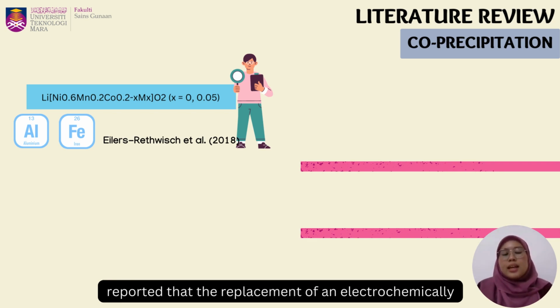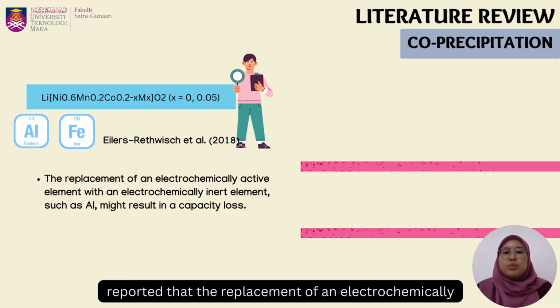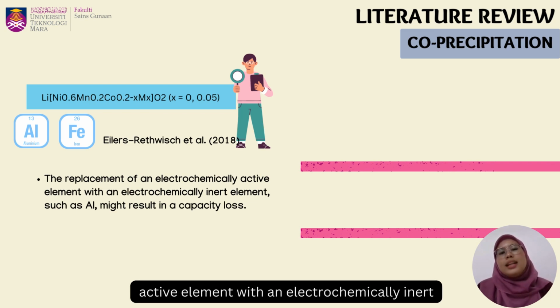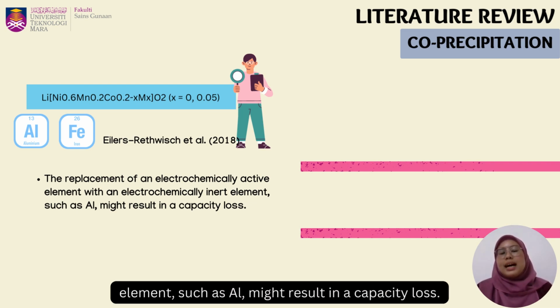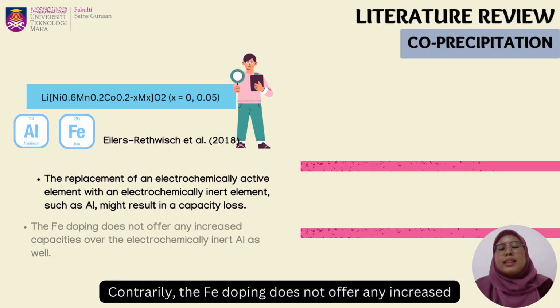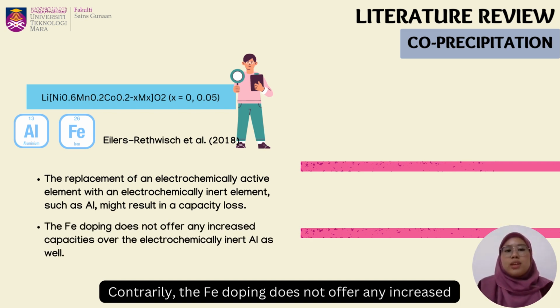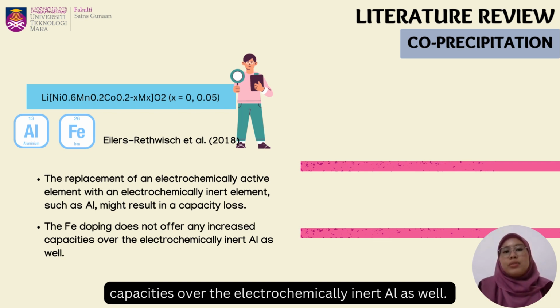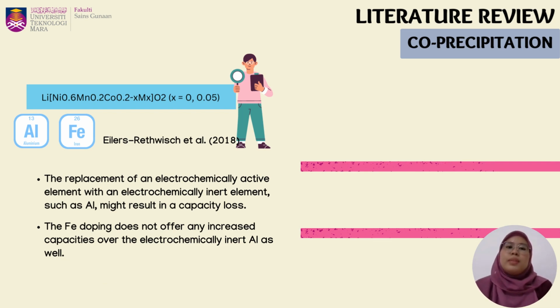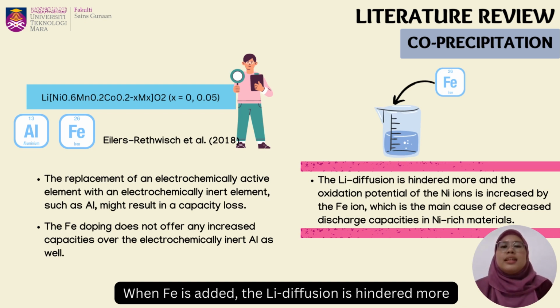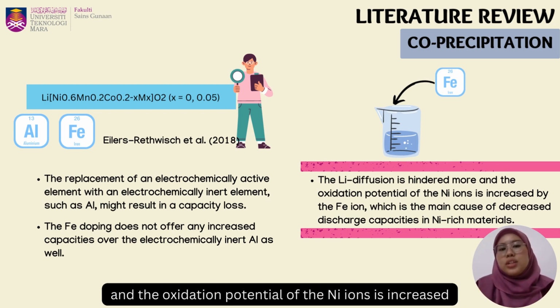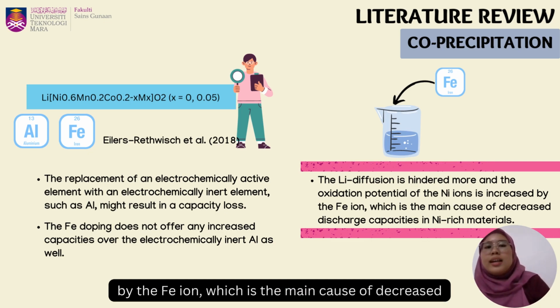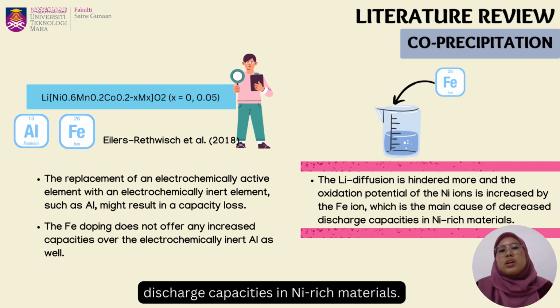It has been reported that the replacement of an electrochemically active element with an electrochemically inert element such as aluminium might result in a capacity loss. Contrarily, the iron doping does not offer any increased capacity over the electrochemically inert aluminium either. When iron is added, the lithium diffusion is hindered more and the oxidation potential of the nickel ion is increased by the iron ion, which is the main cause of decreased discharge capacity in nickel-rich materials.